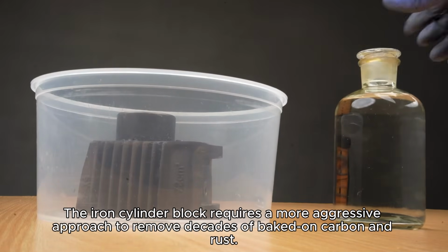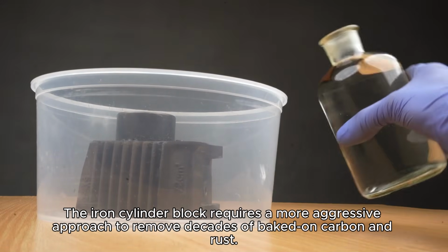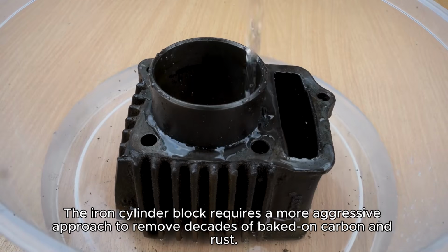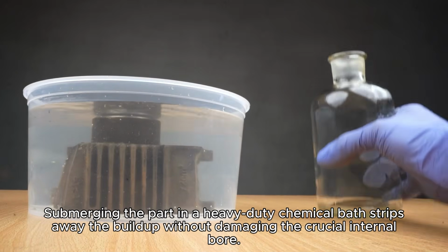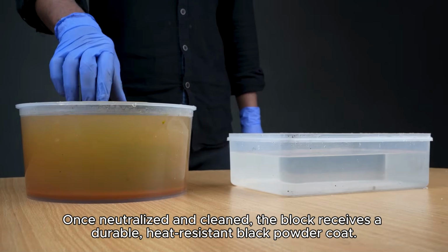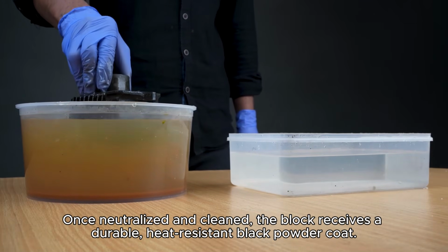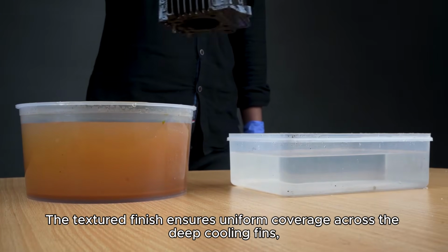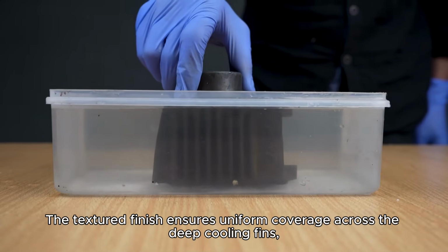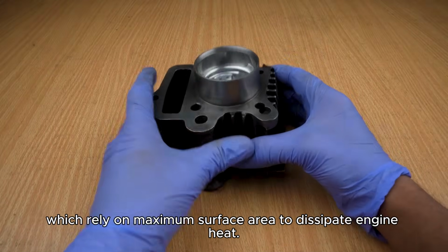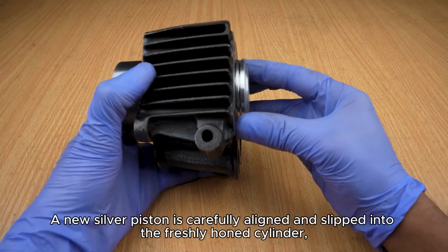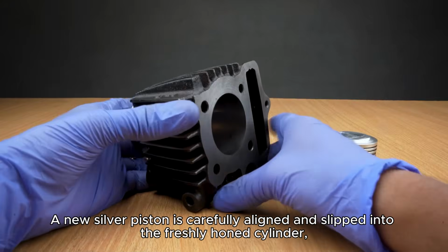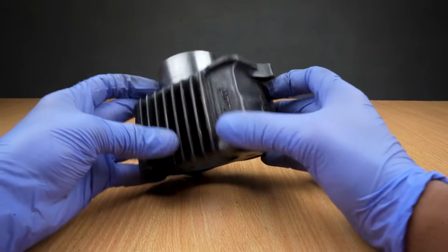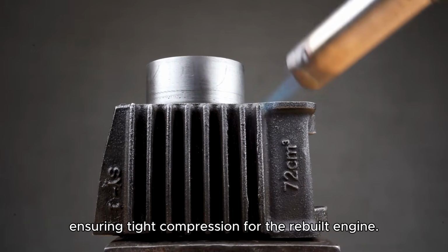The iron cylinder block requires a more aggressive approach to remove decades of baked-on carbon and rust. Submerging the part in a heavy-duty chemical bath strips away the buildup without damaging the crucial internal bore. Once neutralized and cleaned, the block receives a durable, heat-resistant black powder coat. The textured finish ensures uniform coverage across the deep cooling fins, which rely on maximum surface area to dissipate engine heat. A new silver piston is carefully aligned and slipped into the freshly honed cylinder, ensuring tight compression for the rebuilt engine.